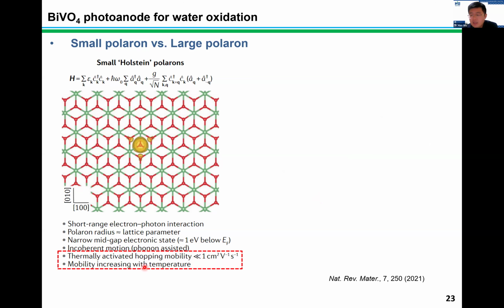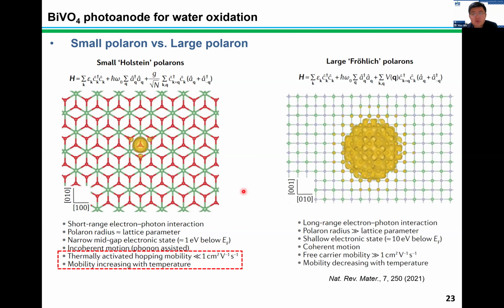with the temperature. On the other hand, for the large polaron, we also call it Fröhlich polaron, its polaron radius generally crosses several lattice units, and it has a free carrier mobility with a value much larger than 1 centimeter square per volt per second, as its mobility generally decreases with the temperature. So here we can see that there are distinct properties between the small and large polarons.